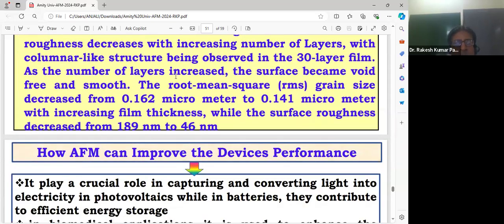And you can calculate the root mean square RMS grain size, which decreased from 0.162 micrometer to 0.141 micrometer with increasing film thickness, while the surface roughness decreased from 189 nanometer to 46 nanometer. So in this way, we have gone through the AFM technique of different films of different layers, and we have observed this.